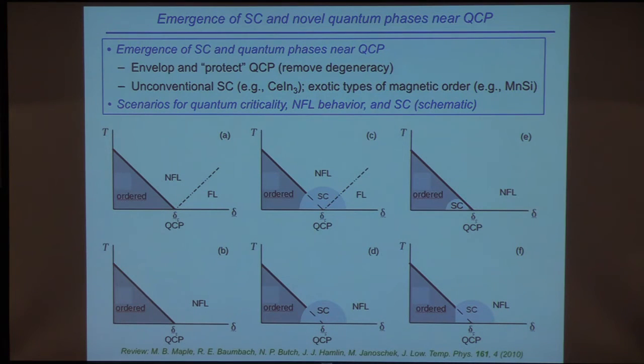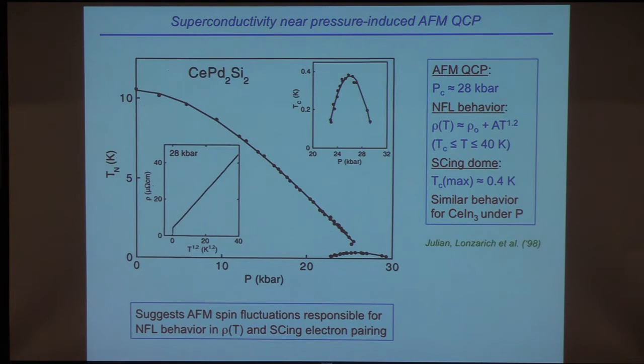Okay. So I'll give you a specific example. Here's cerium palladium-2 silicon-2, so it's an antiferromagnet, and Julian and Lonzarich and co-workers applied pressure and suppressed the Néel temperature, and it looks like it's going to extrapolate to a quantum critical point at about 28 kilobars. And what they found, before they ever get there, is a dome of superconductivity that develops, shown in more detail in the inset. And furthermore, if you look at the resistivity, plotted versus T to the 1.2 power, then this varies as T to the 1.2 between Tc, which is about 0.4 Kelvin, all the way up to 40 Kelvin, and that's non-Fermi liquid-like behavior.